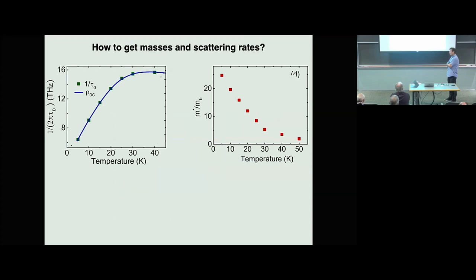So what about specific heat? It's the same lambda at zero frequency that goes into specific heat. It's enhanced. Are you saying if I separate between frequency-dependent tau and what you get at zero frequency? But here it's resistivity. So within the same model, it's the same coupling at zero frequency. The question was that if you attribute the difference between tau and resistivity to m star over m depending on frequency and temperature, then shouldn't the same m star over m go into specific heat? With some approximations or assumptions about the same masses.